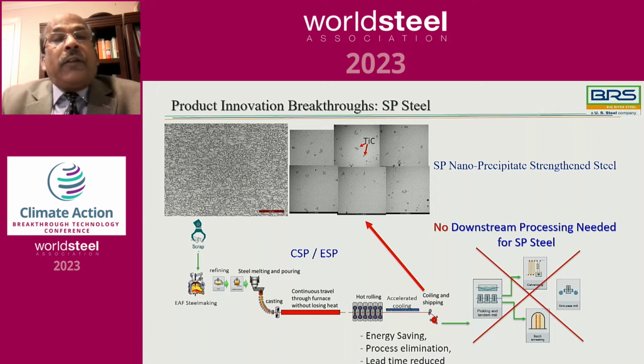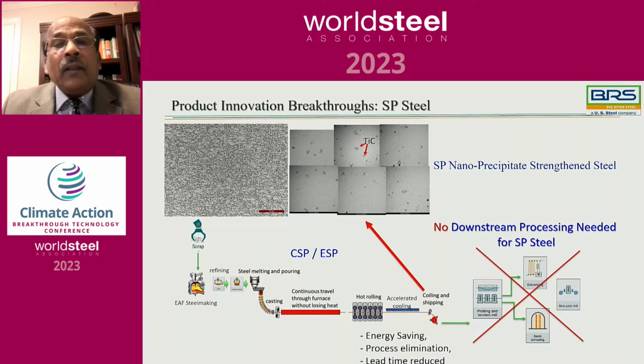The interesting thing is that this whole microstructure is developed only in the hot band coiling stage. We don't need any secondary processing for that. The whole strength is obtained in the hot band coils just by controlling the hot rolling parameters and adapting to that simple chemistry. We call it single phase nanoprecipitate strengthened steel. So no downstream processing is needed to get the strength or the formability in this steel. That causes huge savings in energy, process elimination, lead time, and everything else.